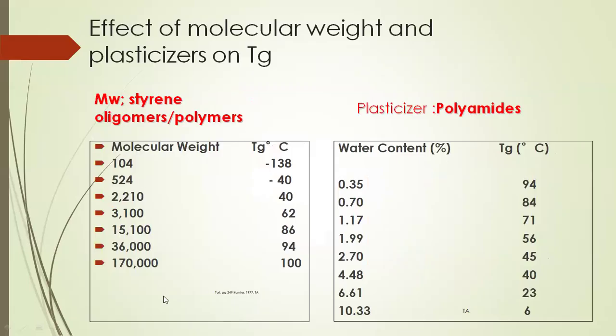If you increase the molecular weight, your glass transition temperature increases. For the same material, if you increase the molecular weight by an order, your TG also increases by 100 degrees, 200 degrees centigrade. A plasticizer decreases the TG. If you increase the plasticizer content, in some cases, let's say for nylon, water is a plasticizer. If you bring a nylon sample and keep it in the open in a rainy season, then if the water content in your nylon changes, the glass transition temperature can vary from plus 94 to 6. That is the huge effect of plasticizers on TG.